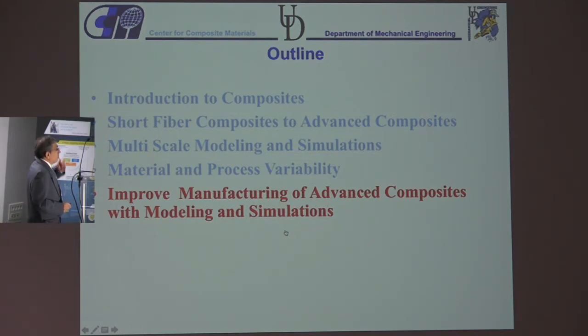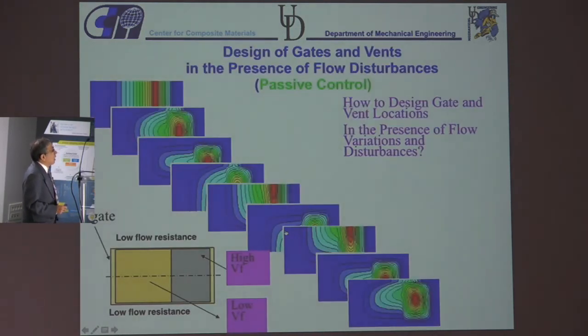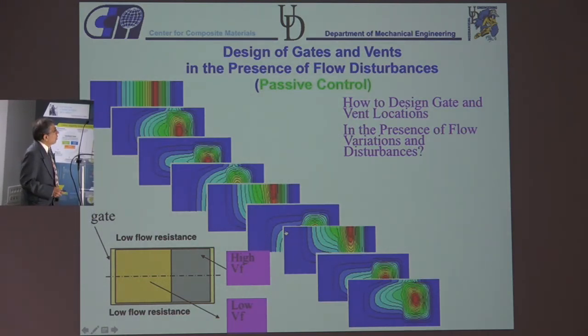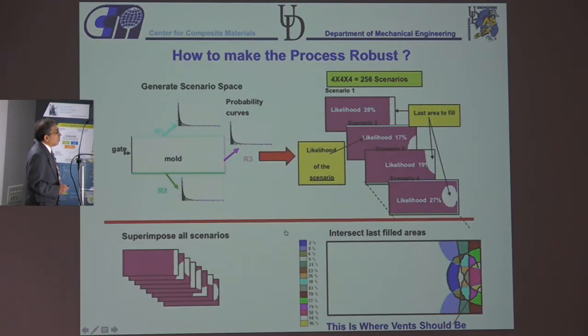Okay, so how can we do that? So some examples. The first case we did was, okay, let's do passive control. So what is passive control? Okay, so I want to make this part. I have high fiber volume fraction in one place, low fiber volume fraction in another place. I could have race tracking at the top. I could have race tracking at the bottom. So what I do is I say, okay, let me look at all the combinations of race tracking, run the simulations for all of them, okay? And then find out what is the best way to put the gate and where is the best way to put the vent.